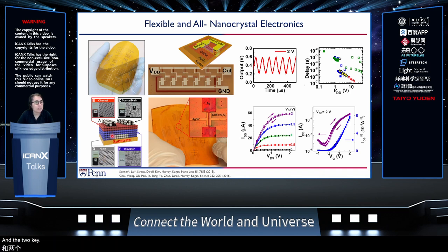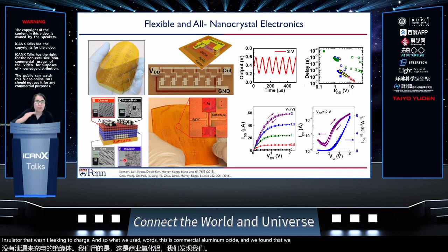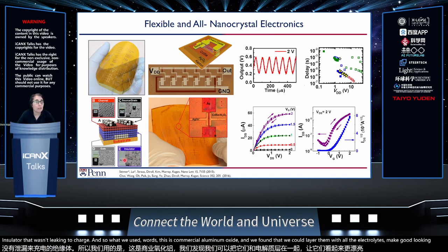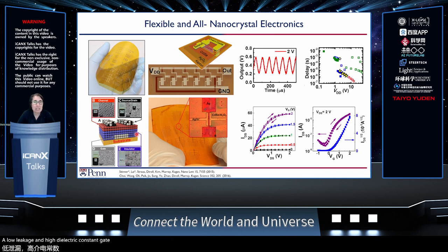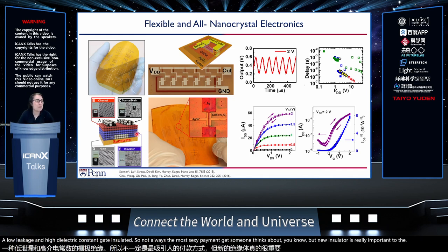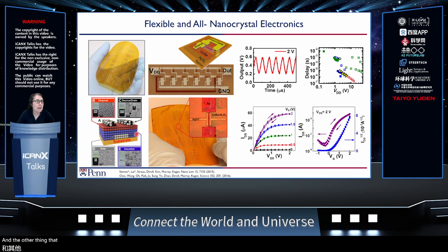The two key ingredients in developing this work that we had to develop at the time were, first, how do you make a good nanocrystal-based insulator that wasn't leaky to charge. What we used was commercial aluminum oxide, and we found that we could layer them with polyelectrolytes to make good-looking, low leakage and high dielectric constant gate insulators. Not always the most sexy thing when someone thinks about it, but the insulator is really important to the performance of the device. And the other thing that we worried about is that we didn't want to, for example, evaporate indium. So at the time, what we did is we introduced and made indium particles by wet chemical synthetic methods.